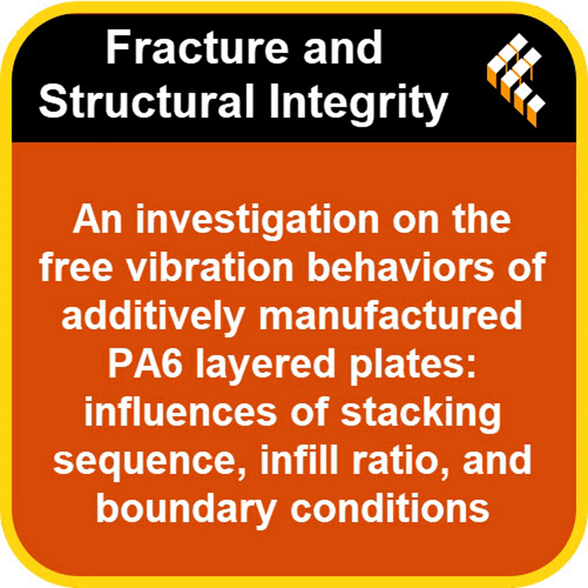Now, if you put the dense high infill layer in the core, like in that 40, 100, 40 setup, you add a lot of mass right there in the middle. And while that layer does add some stiffness to the core, the increase in mass has a more significant impact, tending to lower the natural frequencies. Especially for vibration modes where the center moves a lot. Exactly. Especially for modes where the center of the plate is experiencing large displacements. So it's this clear trade-off. Surface stiffness dramatically boosts rigidity, while core mass primarily adds inertia, which lowers frequency. Fascinating. So it's not just about the total amount of plastic you use, but really about how you engineer its distribution through the layers. That's clever.